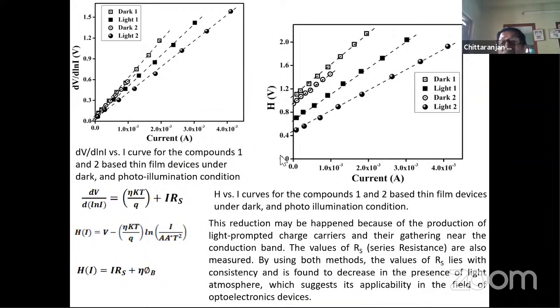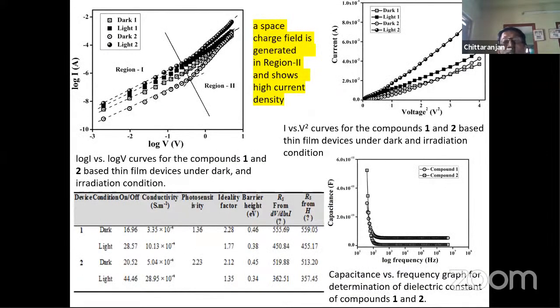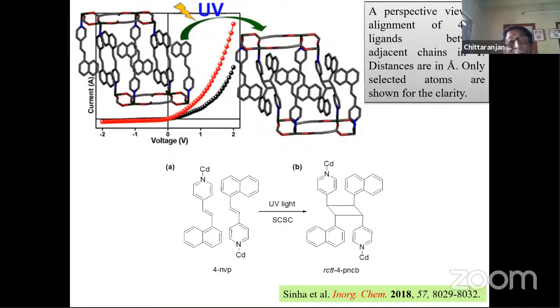Okay, the current-voltage relationship is also in a similar pattern. The first phase follows the ohmic relationship, while the second region does not follow the ohmic relationship, which is known as Schottky diode type behavior. And also the dark phase, light phase activity is similar to earlier, not going into detail. Herein, another interesting feature is light radiation, photoactivation of the molecules. Photoactivation enhances the conductivity. Again, that light energy may be used for some other chemical reactions.